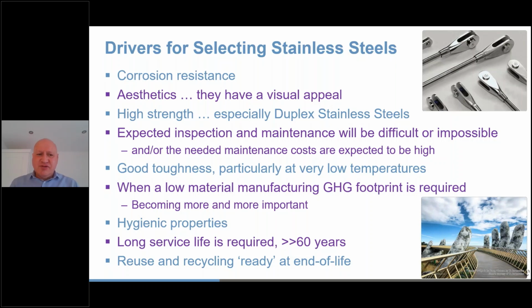The other interesting issue is when you're working in low temperature environments and you want good toughness. Again, it's an important driver for selecting stainless steels, because the austenitic stainless steels don't suffer the ductile to brittle transition, and whilst their strength is not as good as duplex stainless steels, even the duplex stainless steels will work well down to around -50 or -60 degrees centigrade.